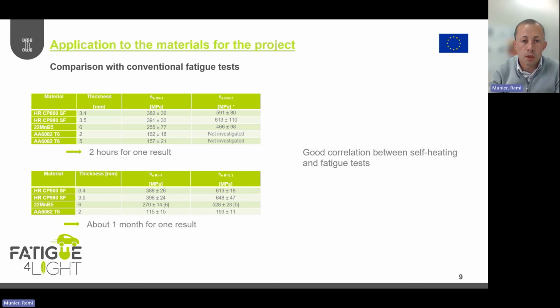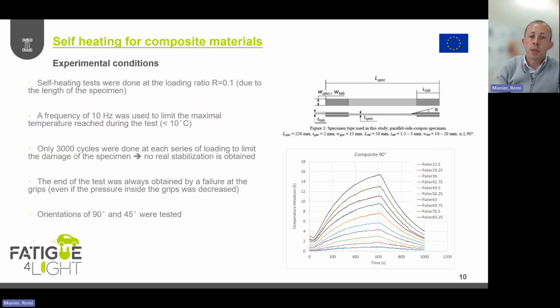Of course, there are some differences, which are very limited according to the time dedicated to the test. So it's okay for metallic materials and aluminum alloys. Then for composite materials, the idea was to test, according to the geometry of the specimen, you can see on the top right, it's not possible for us to test at a -1 loading ratio. So tests were done only at 0.1, and we can observe, as for other materials, a progressive evolution of the temperature of the specimen under cyclic loading.